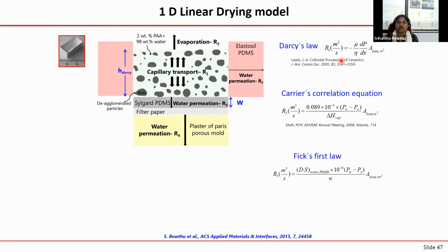Okay, so for the case of R1, the capillary transport, one can model using Darcy's law, and evaporation, one can model using Carrier's correlation equation. This is not a very precise equation because it's more of an empirical equation that people have come up with. So to verify it, I have also experimentally measured the evaporation rates of the slurries for a prolonged period of time by using a high precision weighing balance. And I have corrected that equation by using some factor between the experimental values and theoretical values.